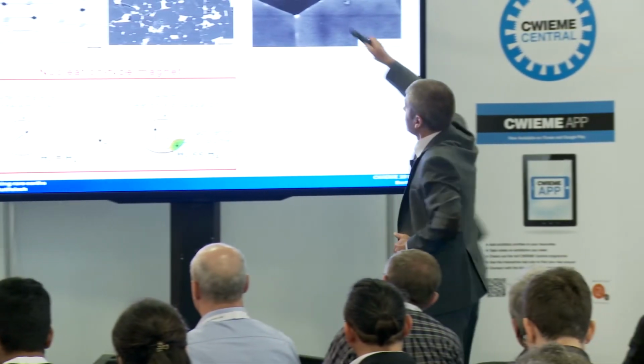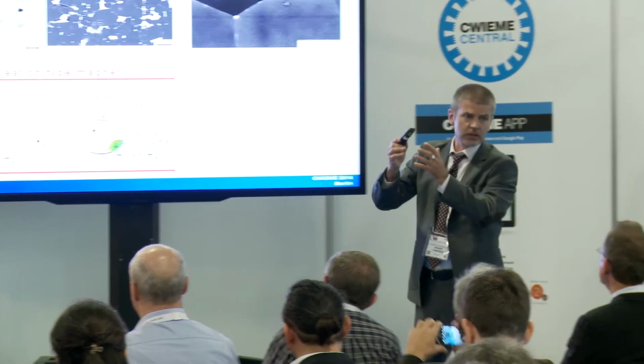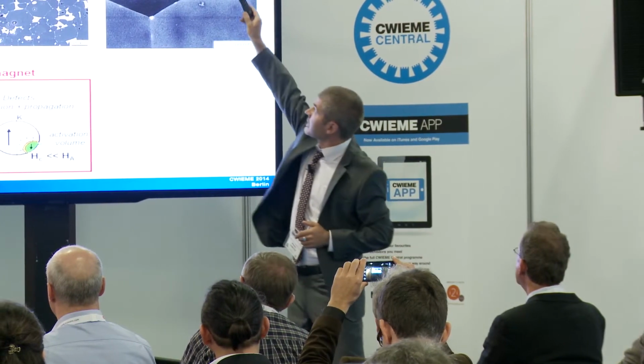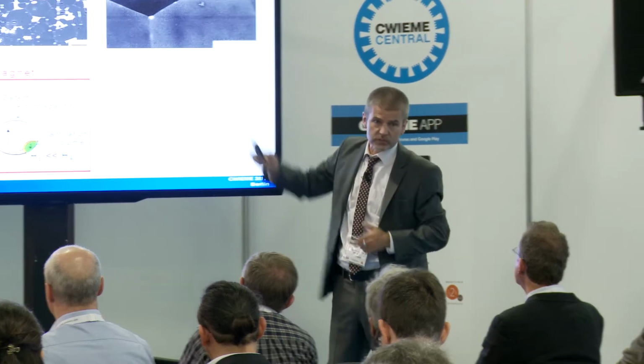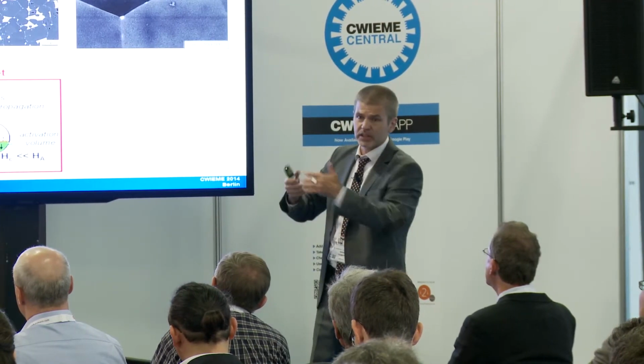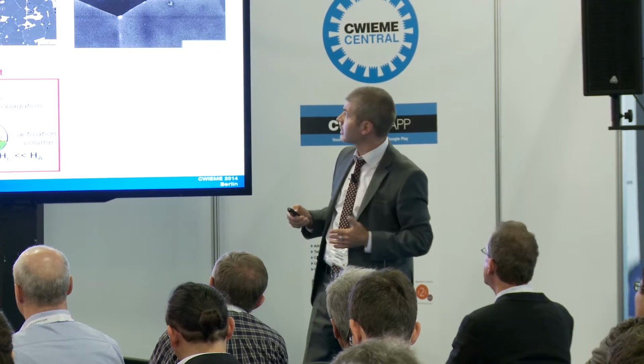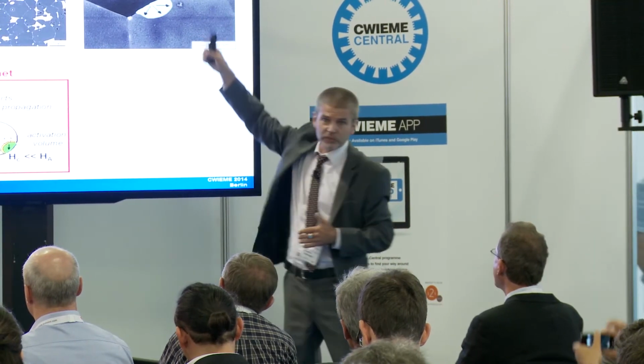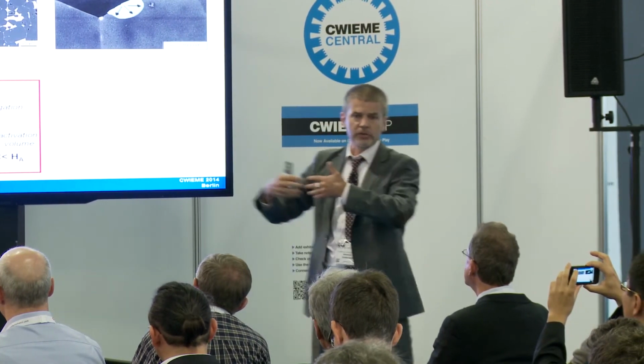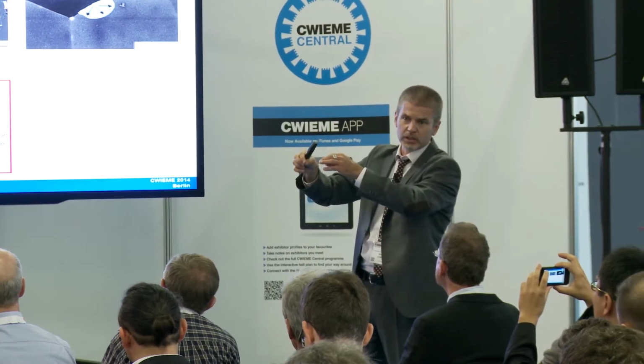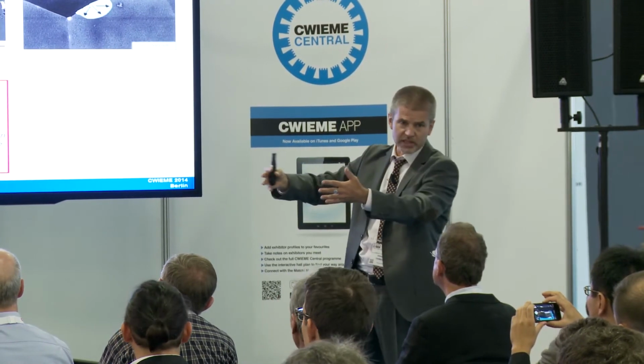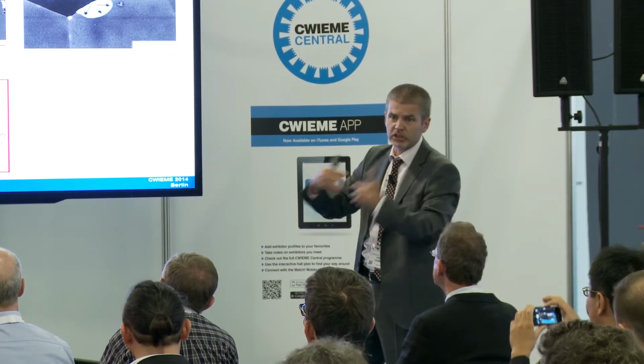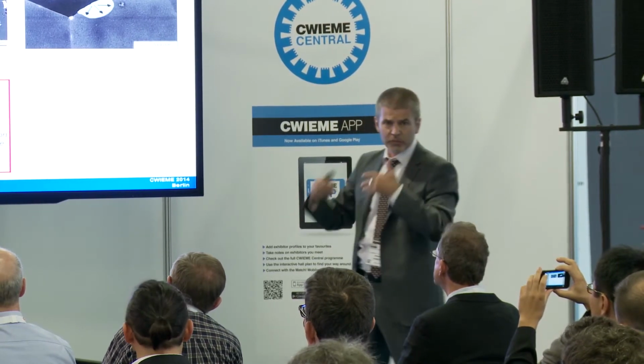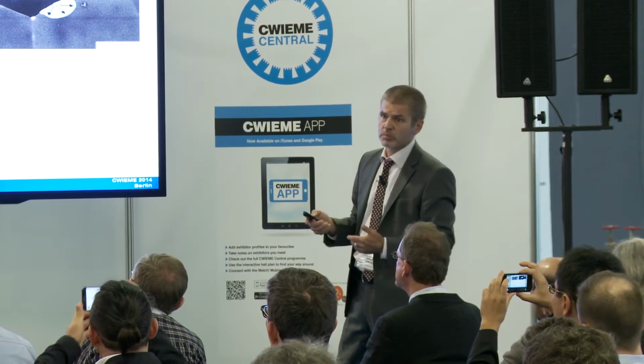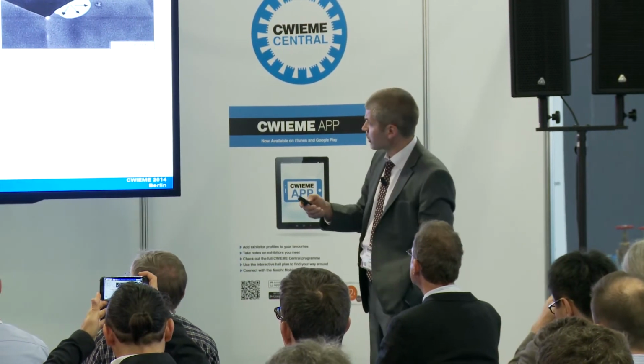Important here is that these little elemental magnets of hard magnetic phase are separated from each other by a rare earth rich phase. So they are magnetically decoupled. But that is also the weak link. Somewhere in a reverse magnetic field, the nucleation of reverse magnetization starts and propagates from there. That is what we need to avoid, and we need to understand why this is happening. If we understand this, then we can use much less of these precious metals.